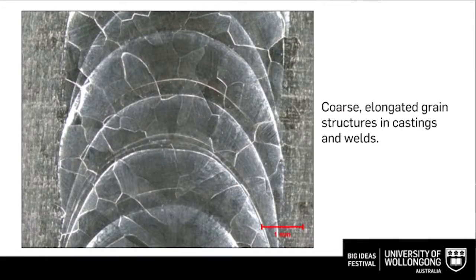This is a typical example of a titanium weld. So you can see the weld in there. And those white lines are the boundaries between the individual grains. If you can look at the scale bar there, that is 1 millimeter. You can see that the grains are quite big, almost on the scale of your soap bubbles. And that is exactly what we don't want. We want those grains to literally be microscopically small.